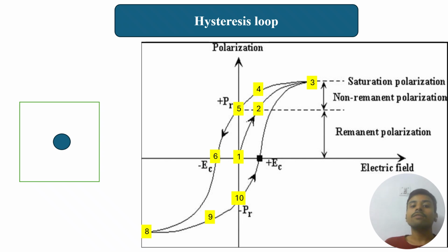But as the electric field is applied in upward direction, the polarization is induced due to the change in the geometrical structure from perfect octahedral to a distorted square pyramid. Here the titanium ion moves in the upward direction along the c-axis, and it tries to reach the face center at the top, leading to structure 3. At this point, titanium can no longer move in the upward direction, thereby leading to a maximum saturation polarization.